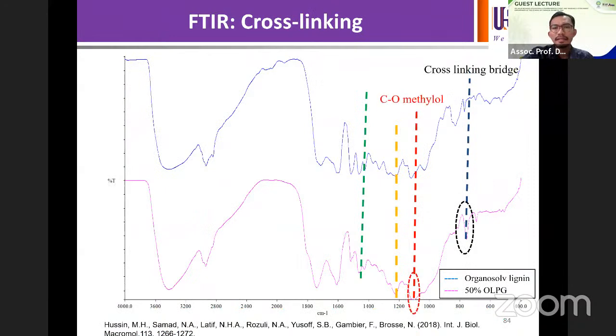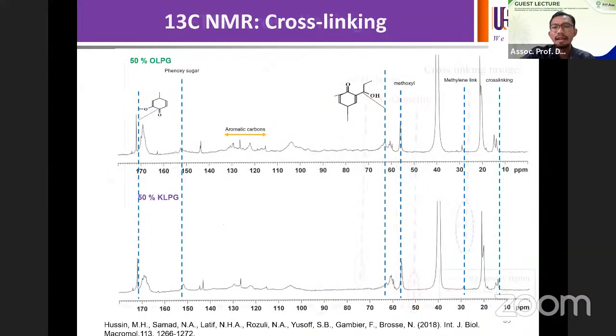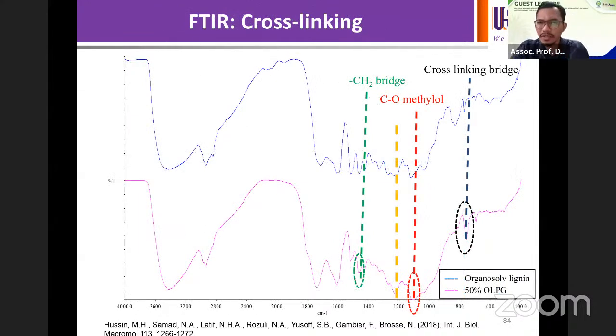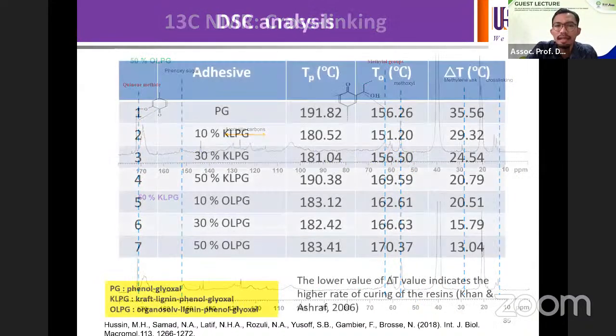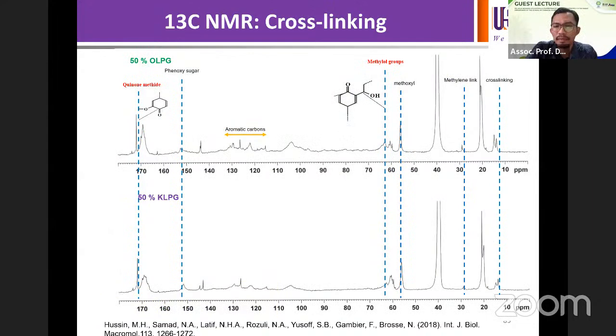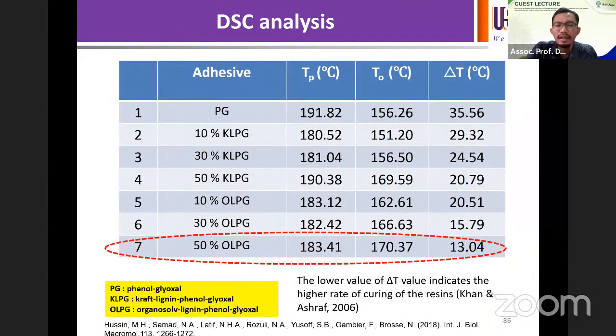So we characterize the adhesive that we have produced. Obviously from the FTIR, we observed the formation of cross-linking bridges, meaning that the resinification process is successful. We also did NMR analysis to double confirm the formation of cross-linking. And we performed DSC analysis to calculate the difference of temperature. If you obtain a lower delta T value, it indicates a higher rate of curing of the resin. This supports our previous characterization in terms of the gel time and also the viscosity.